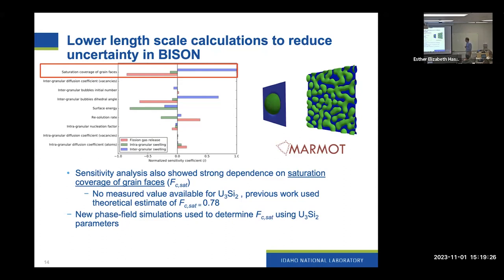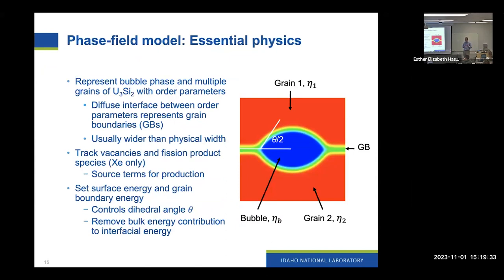So we wanted to use phase field simulations to try to determine that value and inform the Bison model. So to do that, we're using a phase field model. And I know not everyone in here is a phase field modeler, so I'll try to say a little bit more about how we represent the microstructure of the fuel within the phase field context. So what we do is we have a so-called order parameter that represents what phase the material is in at each position. So say for grain one, we have an order parameter η1, and that has a value of one inside that grain. We have another grain of the fuel, call that grain two, which has an order parameter associated with it of η2.